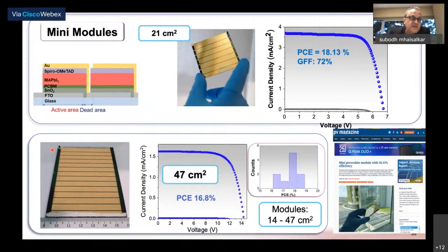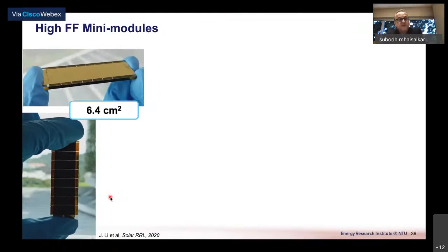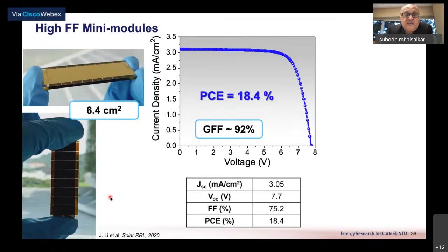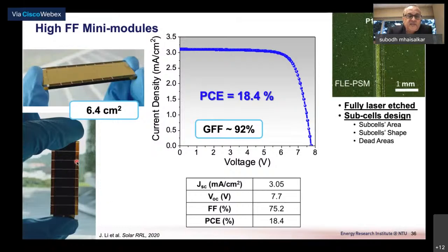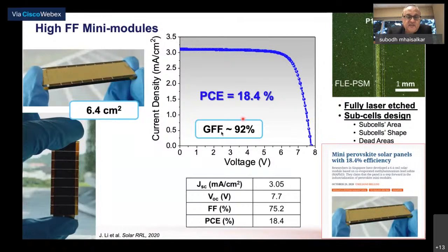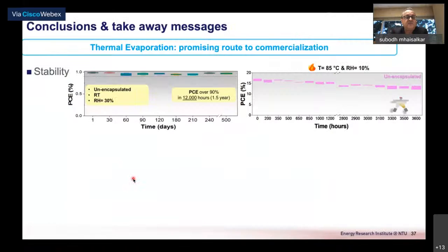At this point, the evaporator that we have limits us to a maximum size of about 40 to 50 centimeters square. And we are in the process of commissioning a new tool that will allow us compatibility with more than 250 centimeters square or 6-inch substrates. But before we get there and scale, we have continued to work on optimization of the mini modules. Now we have just implemented a full laser process where we scribe all the individual layers using lasers. With this, we have been able to increase the geometric fill factors to the 92% range, and PCEs for a 6 centimeter plus device are in excess of 18%.